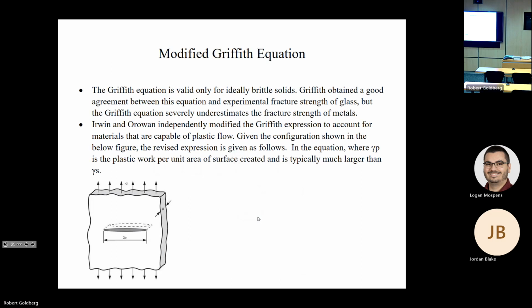Okay. So moving on. From the original Griffith equation, there were modifications that were made. The Griffith equation, as developed and we talked about, is valid only for ideally brittle solids. When you look at glass, which is the stereotypical brittle material, Griffith obtained a good agreement between his equation and the experimental fracture strength of glass, but the Griffith equation severely underestimates the fracture strength of metals because obviously metals are not brittle, they're ductile. And at a point, you even have local plasticity in there, which we'll talk about a little bit.